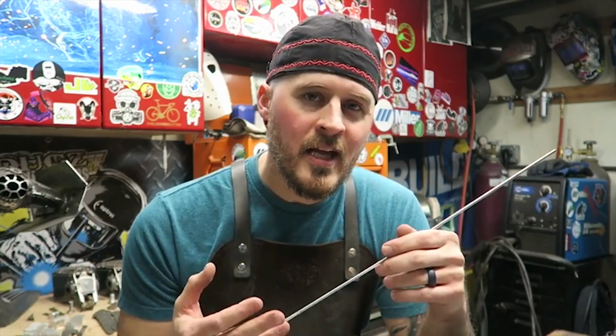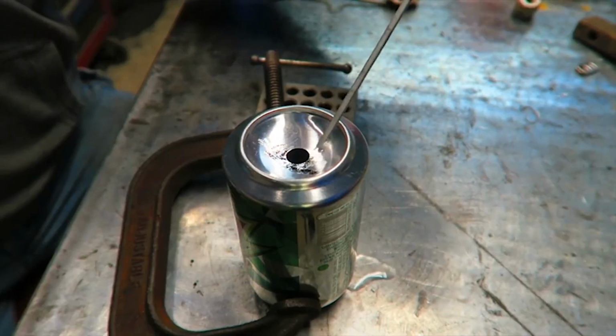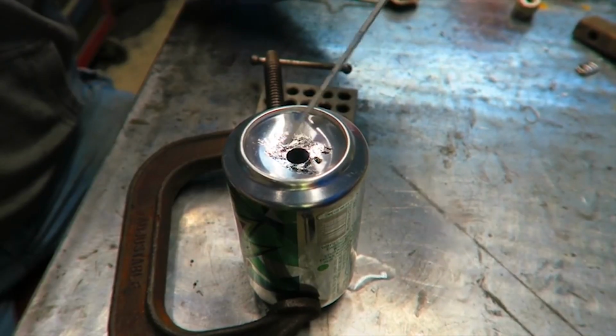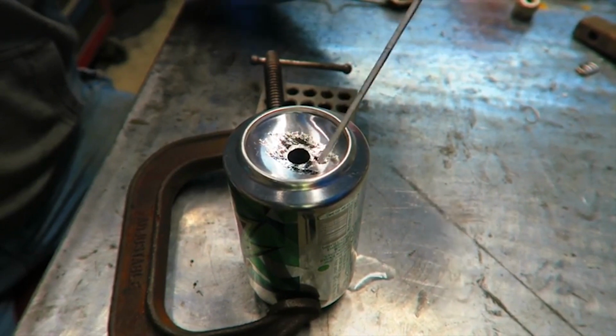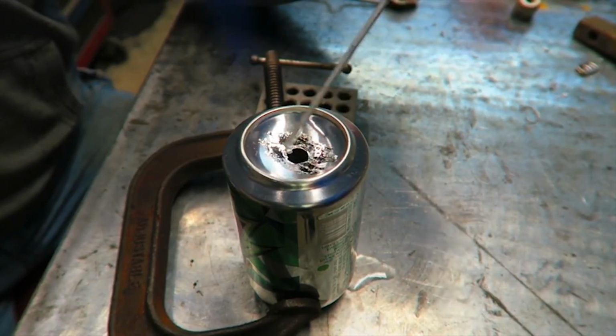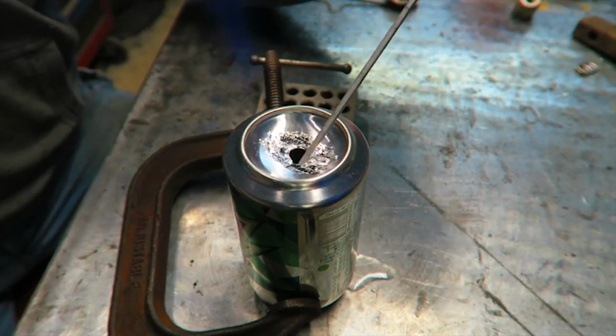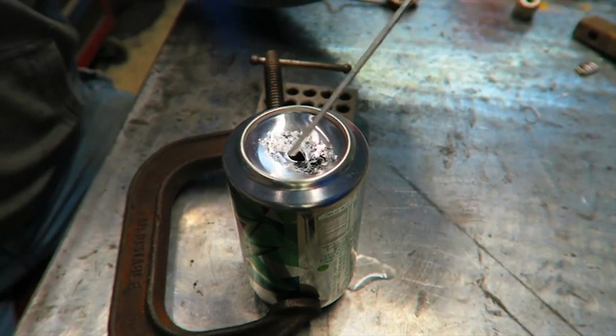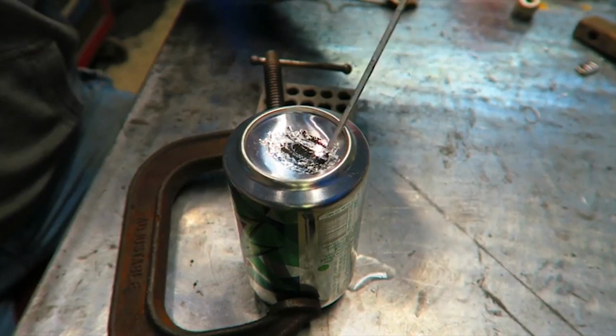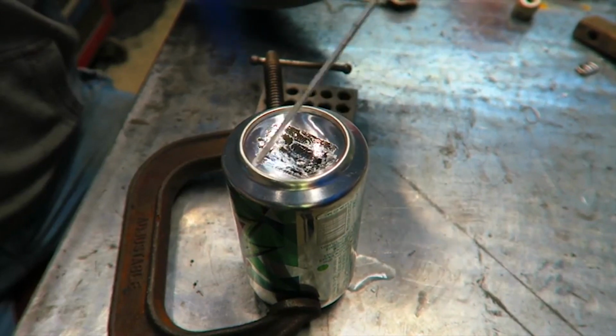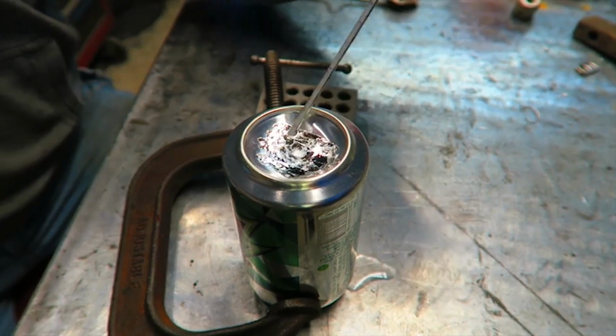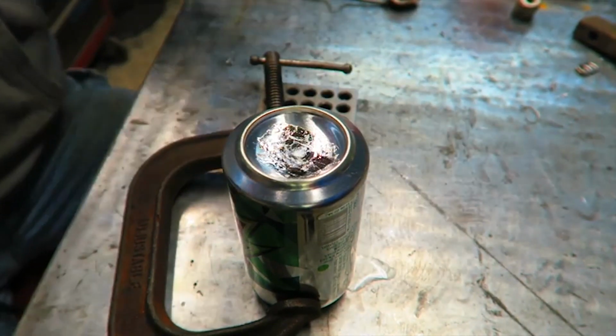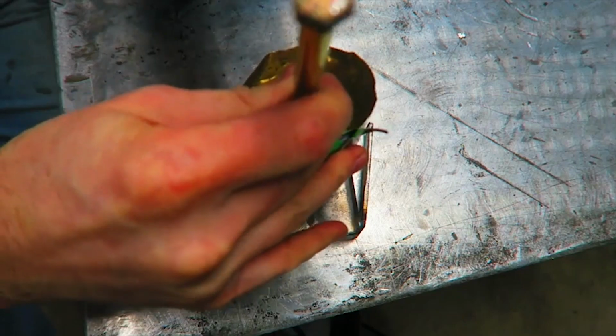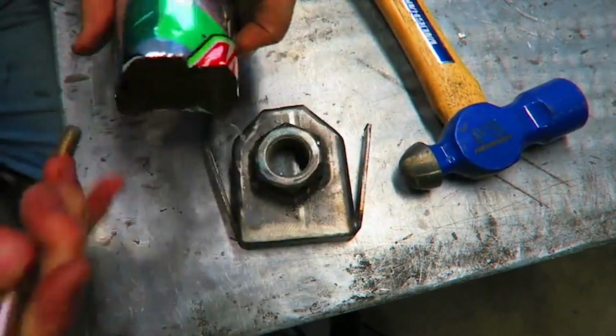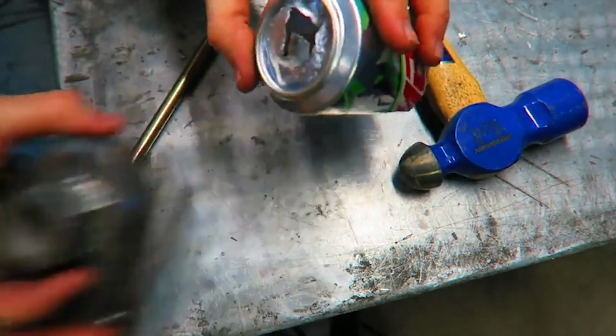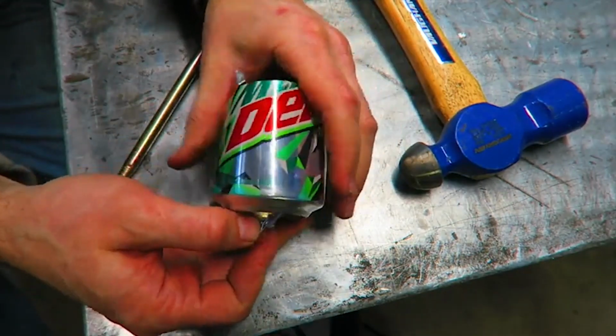Very carefully heat the base metal, moving the rod back and forth until I see the rod start to melt. I tin the surrounding areas, and then swiping the rod quickly across the hole, you will see the surface tension of this brazing rod is high enough that it will easily fill gaps of upwards of 3/8 of an inch with no backing material whatsoever. By trying to drive the repair out of the bottom of this can, you will see the can tears first before the repair itself tears.